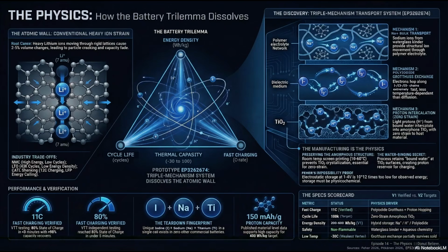150 milliamp hours per gram translates to roughly 390.9 watt-hours per kilogram at the material level. That is knocking right on the door of Donut Lab's seemingly impossible 400 watt-hours per kilogram claim. But the real magic of utilizing the proton isn't just the sheer capacity. It's how it completely rewrites the rules of the battery trilemma we discussed earlier. Let's look at those constraints again, starting with energy density versus cycle life. Right, the structural violence problem, the expanding Jenga tower, the cracking glass maze.